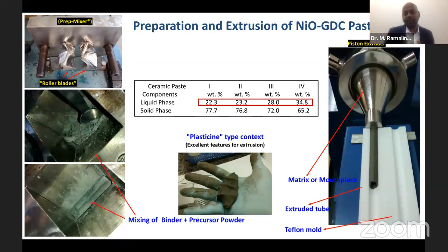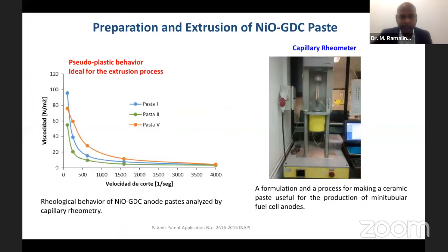With size reduction, obviously we can stack more cells in 1 cubic centimeter. That's our aim, for example some 9 cells in 1 cubic centimeter, which is a kind of integration of cells. So we fabricate this material by the extrusion process. And of course, we also characterize this paste using different equipment like viscometers, to maintain the viscosity and other properties, such as plasticity, of the materials.